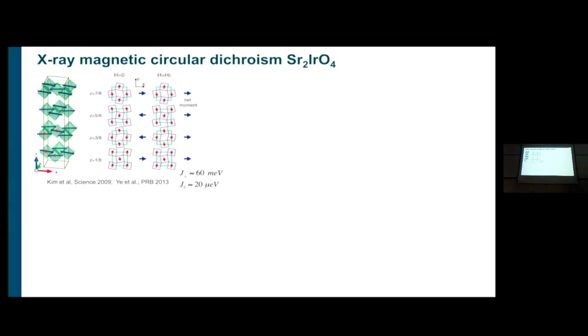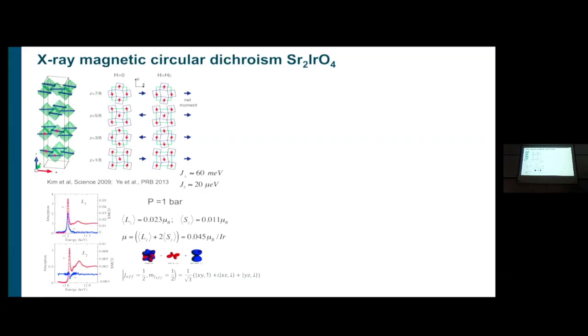But if you apply a very small field, the exchange coupling across the layers is extremely weak, micro eV energy range. So a very small field of 0.2 Tesla or so causes the layers to rearrange so that the little canted moments are now aligned and you get a net moment. It's very small, but you can measure it with XMCD, and then you can use some rules to separate the spin and orbital moment.